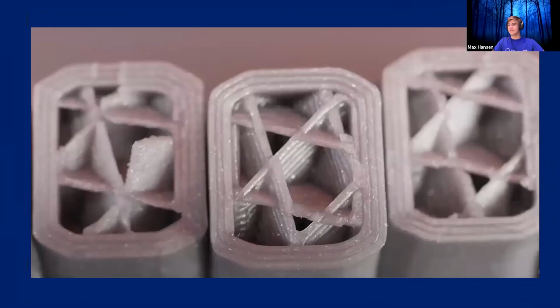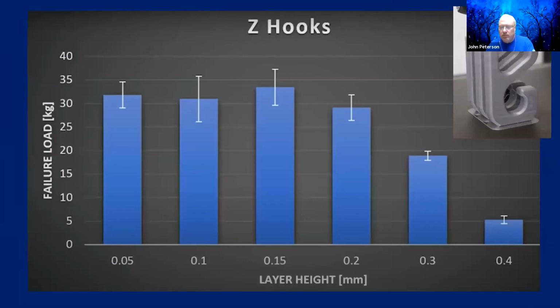And then when we look at the Z hooks, can you go back one slide, Mr. Peterson? When you look at the Z hooks here, you can see again that the 0.1 and 0.15 millimeter layer heights tend to be the strongest. But most importantly, if you look over here at the failure load, you can see it's almost half, or in some cases less than half of the other one when it's printed on the XY axis, which is an incredibly drastic change and something to keep in mind. And as well, you can see down here where it gets to the 0.4 and the really thick, this really drops off and becomes a lot less strong and much more prone to breaking.